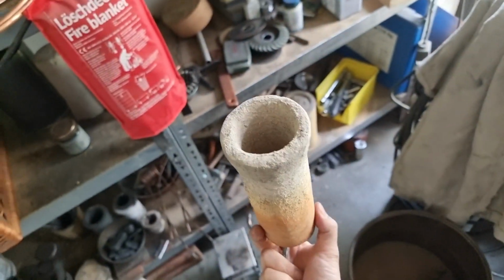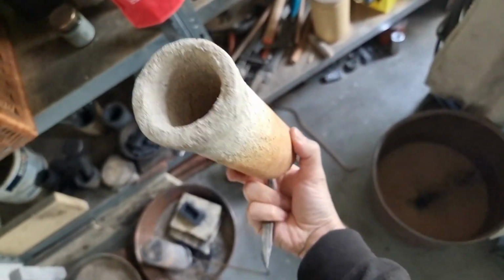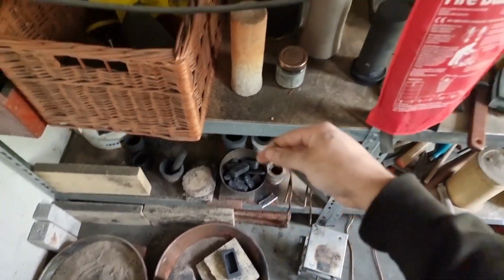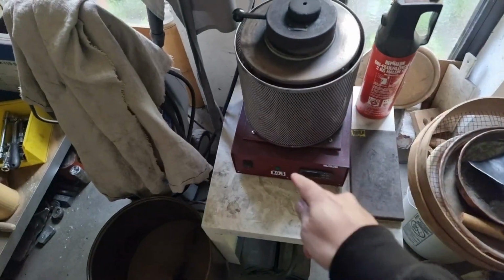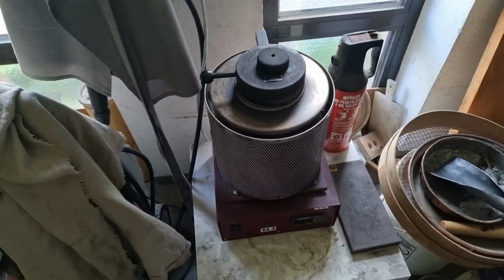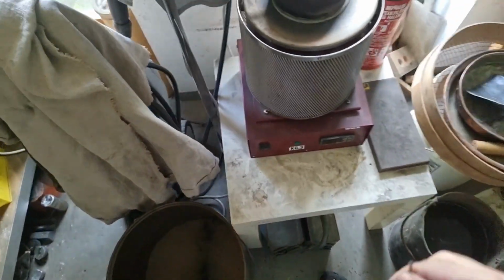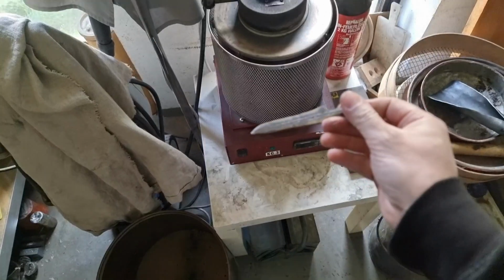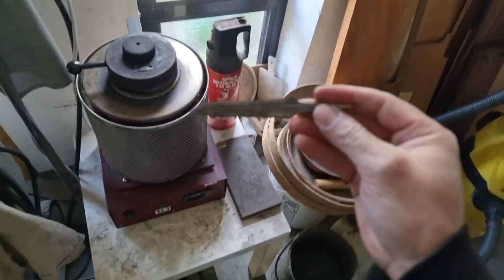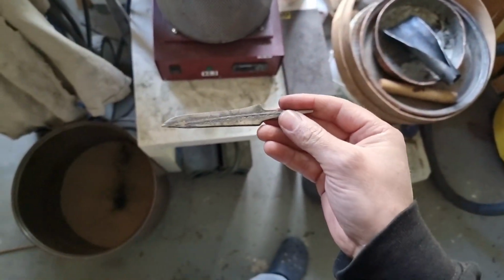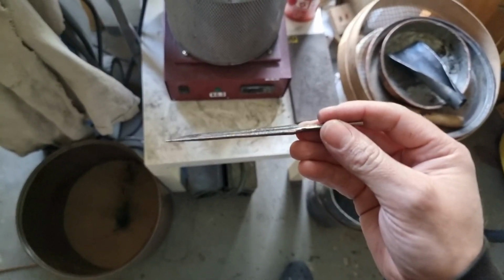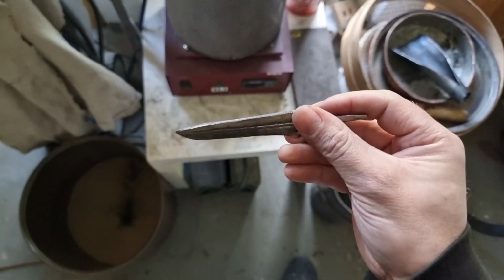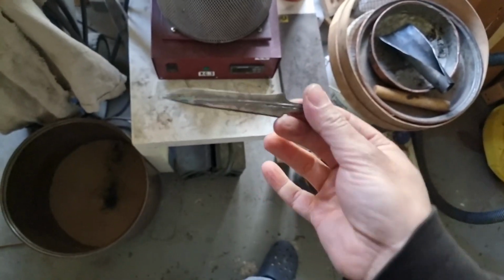This is a blade I cast from that white cast iron, and then I put that blade in this crucible here, that is also a heat resistant clay crucible I made myself. I filled that with plain sand, and then I put that knife inside the sand, and then I put it in my electric furnace for 6 hours at 950 centigrade, and that essentially removed the carbon from the surface of the knife, and also by a diffusion process reduced the overall content of carbon in that blade, converting it essentially into steel.